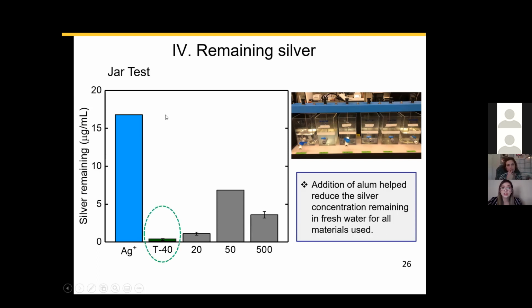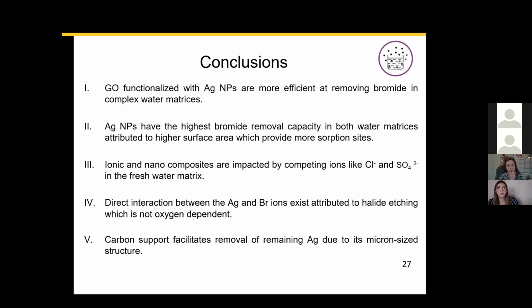If we take a closer look, we see that the graphene oxide silver nanocomposite is the most effective at slowing down or preventing that silver from being released into the water stream. That's attributed to the fact that it has this carbon support, which, because of its micron size, can be easily coagulated and settled down after the addition of alum. So based on this work, we can conclude that the graphene oxide functionalized with silver nanoparticles is efficient at removing bromide from complex water matrices.